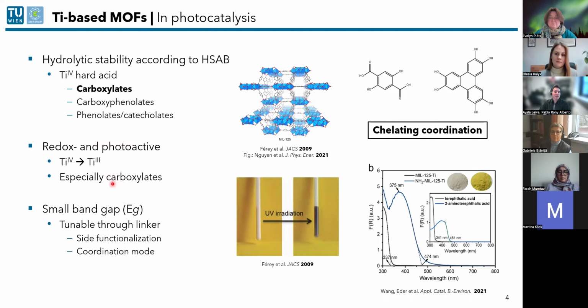Another thing that is advantageous about titanium-based MOFs is that you can tune their band gap, so you can make them absorb low energy light. So this tunability can happen through the linker, so either through side functionalizations or through the coordination mode. And we have also shown already a few works here when we used amino functionalization for MIL-125, and we narrowed the band gap. We improved the absorption properties of this material. And now when you have generated charges, you also want to separate them and extract them. So what about this component?